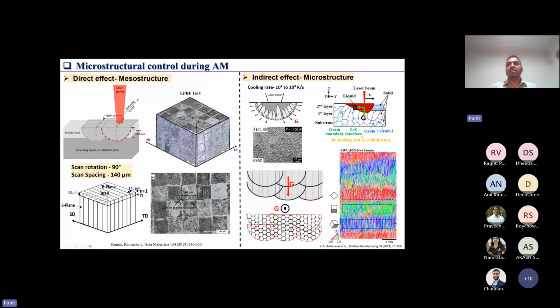The direction of the thermal gradient you can control by controlling how fast your laser beam is moving and what the laser power is. Here I am showing two examples where the direction of G is changed. Here the G direction is going in the way the red line is showing, and here the G direction is perpendicular to the plane.